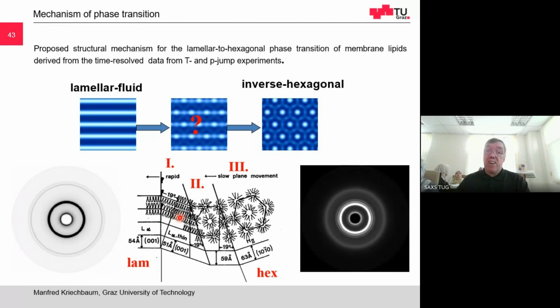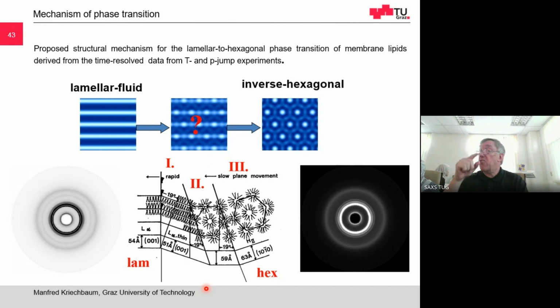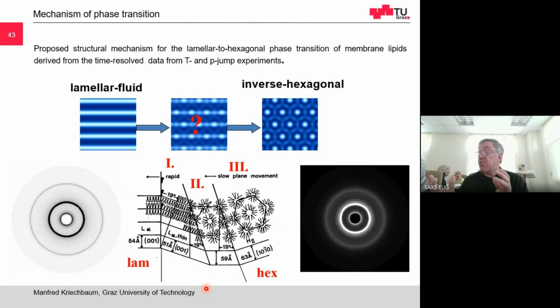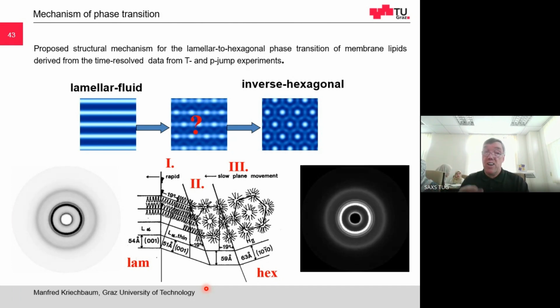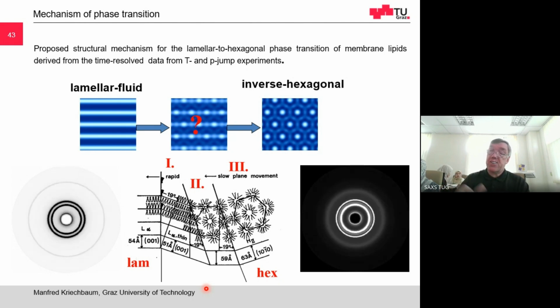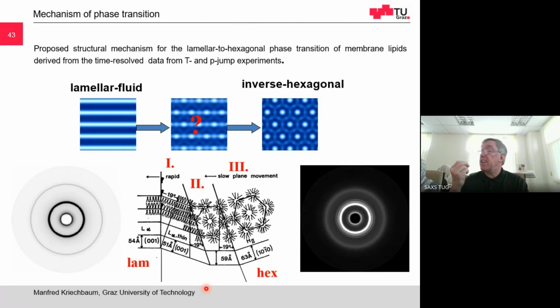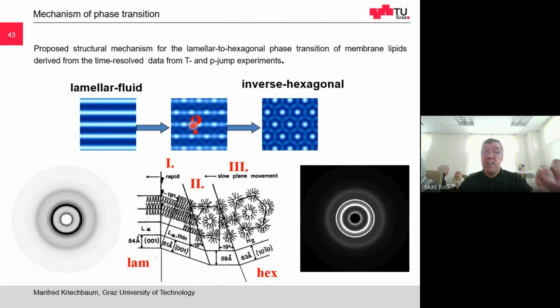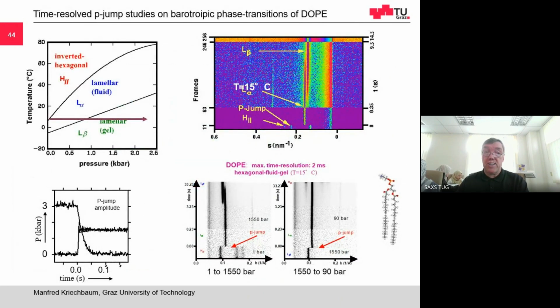And then you can also sketch how this transition is occurring. Like from the lamellar phase, it has to undergo the transition into a smaller lamellar phase, and only then can it proceed into the hexagonal phase. So there is some disorder. There is basically a transient state, an intermediate state. The intermediate state from here to here is a thinner lamellar phase, in order to get into the hexagonal phase. Okay, here are some diagrams.